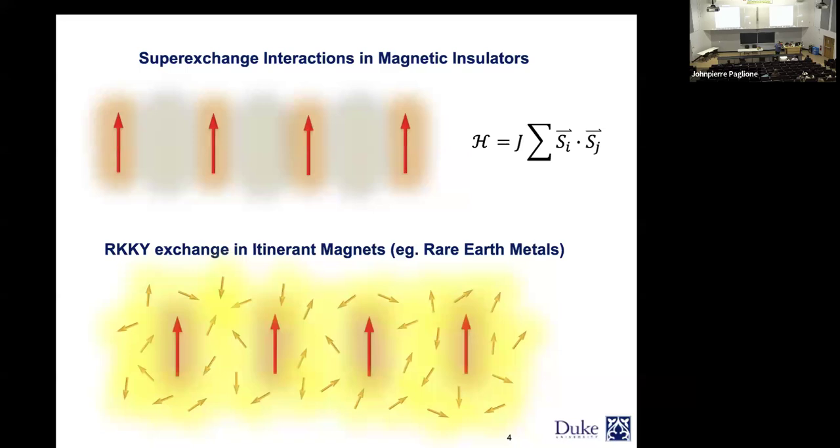Okay? So this exchange is mainly what we focus on today, and this is basically for most of the insulator compounds. But if you have a compound that's metallic or has charge carriers, then here are my spins sitting, decorated in a chain, and the interaction in the case of RKKY is through these mobile electrons that can see what kind of interaction this spin has, act as an agent, and tell the next site, okay, you have to be ferromagnetic.